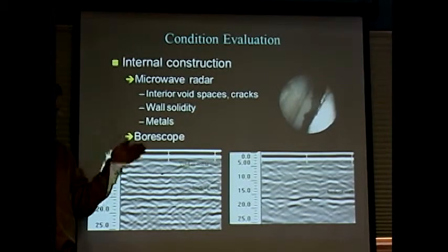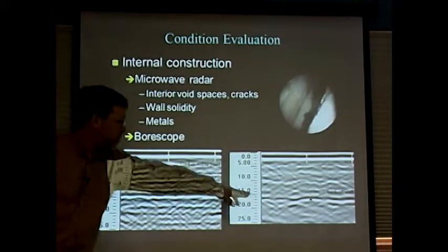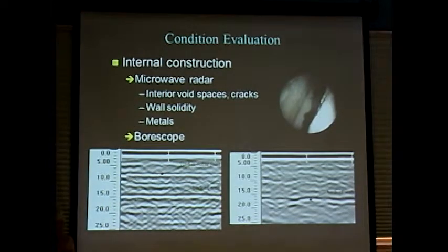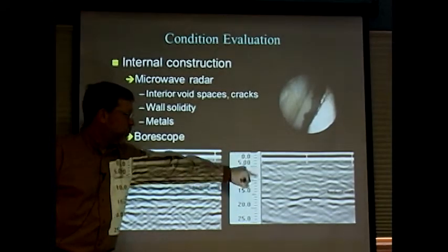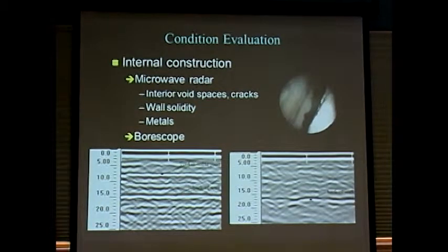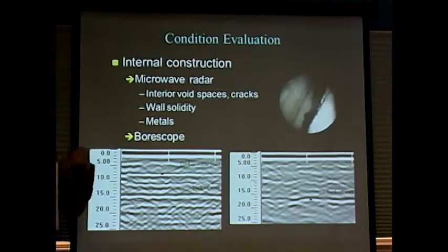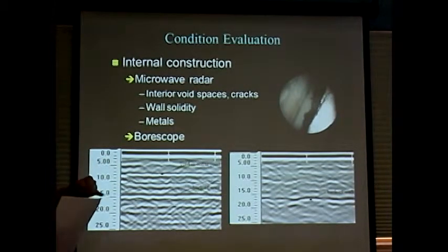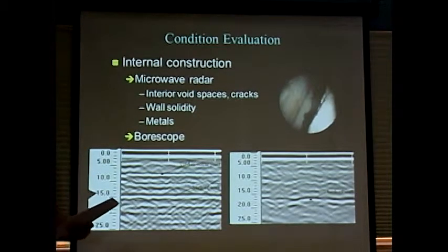We're sending this radar trace through 4 wythes of brick and getting a reasonable reflection from the back of the wall there, and not many reflections from the interior wythes, and that to me means a pretty solid wall. This other radar trace here on the left, you see our depth estimate is a little bit off. It's because we're passing through a whole series of air voids within the wall construction. So using radar scans, we didn't scan the whole building, but 10 representative areas, say, we got a pretty good idea of the distribution of voids in the collar joints and how those voids existed throughout the building.